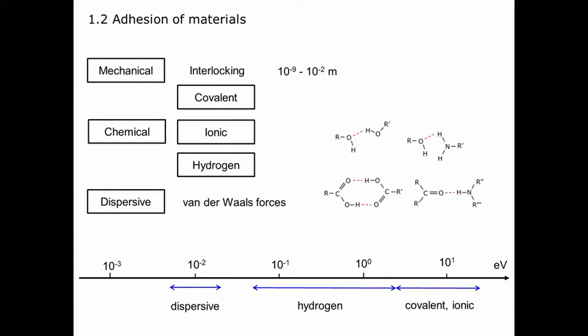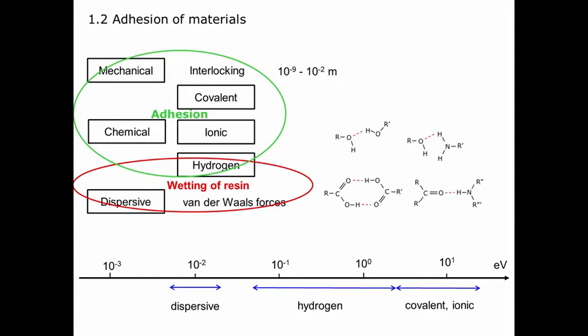However, we cannot forget about the dispersive force. It is a very weak van der Waals force. But in reality, for the adhesion, you introduce a resin or adhesive to the surface, and then there's the problem of wetting at the beginning. If wetting is not good, then you will create a lot of tiny defects or voids that will be quite problematic for the adhesion. And if it is wetting, both hydrogen bond and dispersive forces are the controlling parameters. Then after curing, gluing, stronger interactions with mechanical and chemical effects play an important role. That's the adhesion.